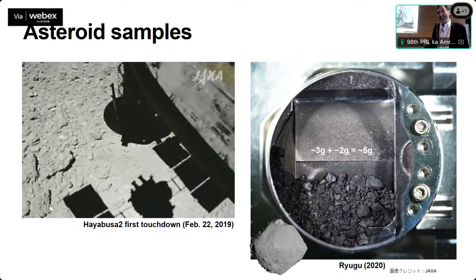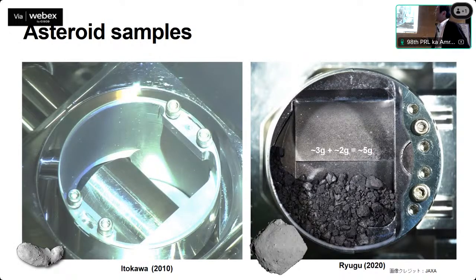So this is the Hayabusa 2 case. But in the Hayabusa 1 case, the shooting of the bullet failed. So we could not make an impact. Therefore, this is the Hayabusa 1 case. The capsule is the same. The diameter is about 5 centimeters. So you see, there are no samples of a size we can see by eye. So we tried to find samples in this room for 2 months for Hayabusa 1, but found nothing.